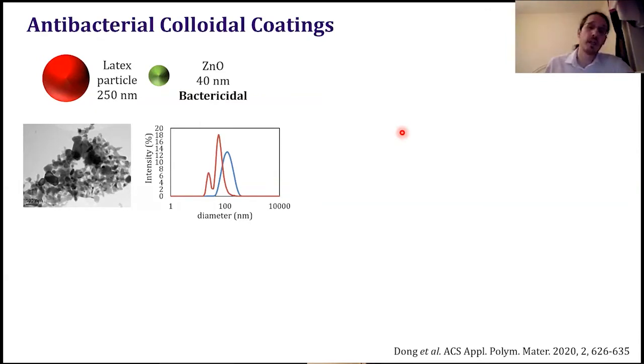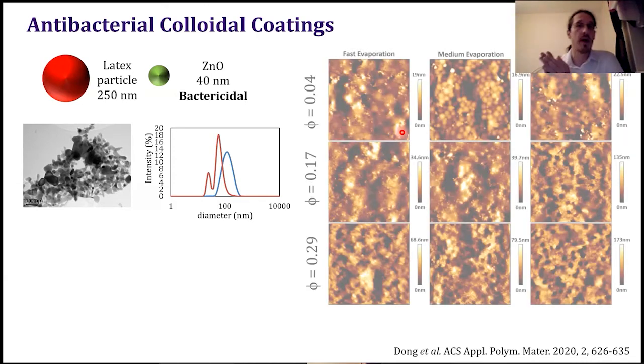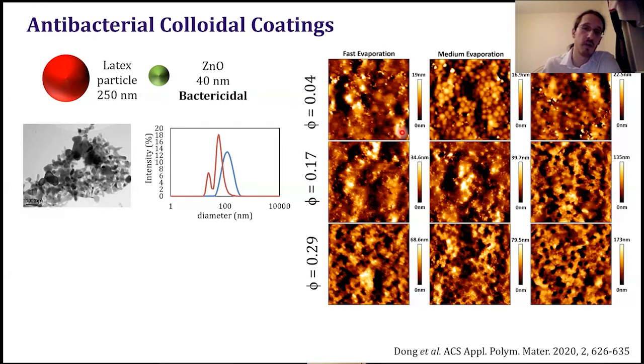And then what she did is, and this is something that you will see over and over during the talk, play with how fast we evaporate that coating. So she had different concentrations. This is the volume that is occupied by the zinc oxide in the dry film, so 4%, 17%, 29%. And these are different evaporation rates.